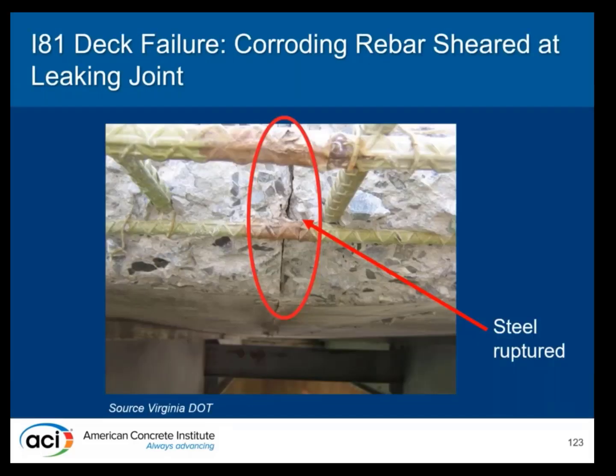So what can that look like? This is a picture from VDOT where there's very concentrated cracking at a leaking deck joint. And actually, that concentrated corrosion led to the reinforcing steel shearing or rupturing at the deck, at the joint level.